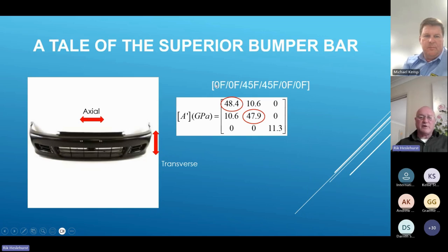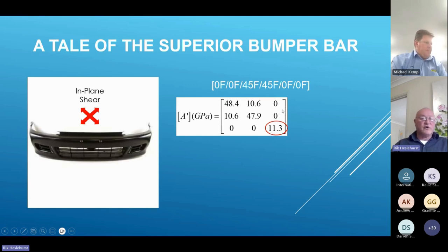And the configuration out of an 800 satin carbon fiber weave was 0, 0, 45, 45, 0, 0. So the zeros are all across the front, 90 degrees is vertical, and 45 is obviously at 45 degrees to that. Now, I ran the analysis for them on that material, and this is what is called the in-plane stiffness matrix. 48.4 is effectively the Young's modulus in the axial direction. 47.9 is effectively the Young's modulus in the transverse direction. And the in-plane shear modulus is 11.3 based on the 45-degree plies.